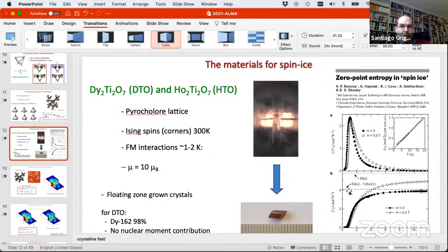For example, some of our previous work was on strontium titanate, and it was a real nightmare to get a good single crystal. Here, the first time we decided to start working on something like spin ice, I put that as a summer student project to grow the crystals, and she was a very talented summer student, but an undergraduate managed to grow these crystals within a couple of months.